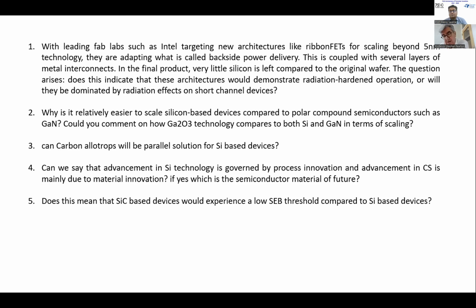I don't want to antagonize the diamond folks or the boron nitride folks, but I don't see 12-inch diamond substrates. I just don't see that. Boron nitride still is difficult to grow in any reasonable form. So the one thing that's really critical is to have a substrate, right? So once you have a substrate, you can grow epi of the same diameter, and then you can do band gap engineering, all of this stuff.